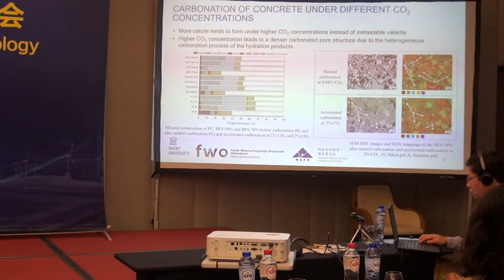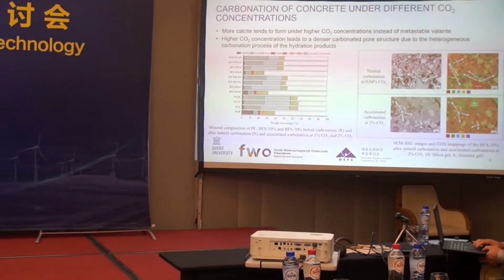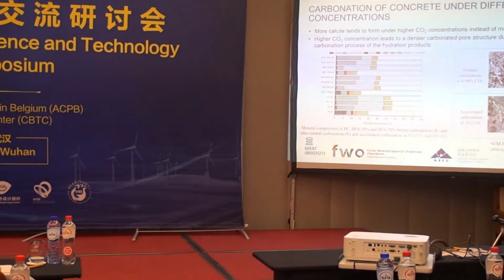He also looked at the densification, and especially when you look at natural versus accelerated carbonation, with accelerated carbonation you see more densification of the concrete itself. So this can be studied, for instance, with scanning electron microscopy.